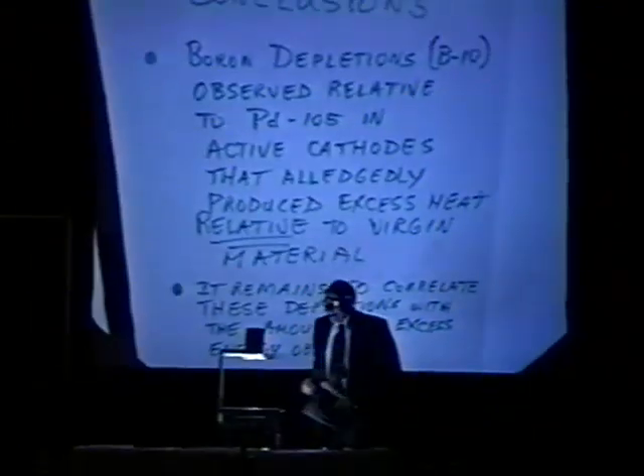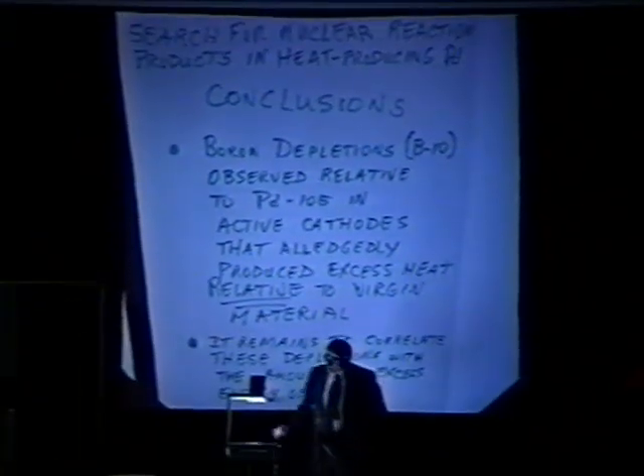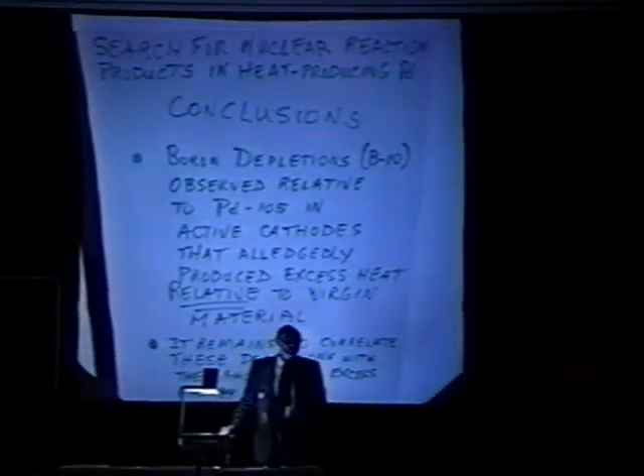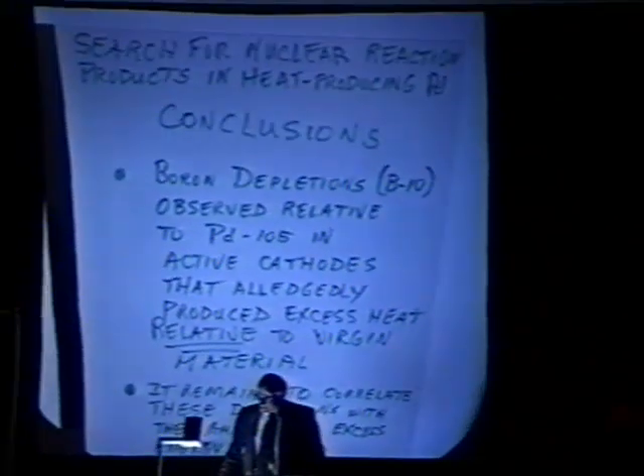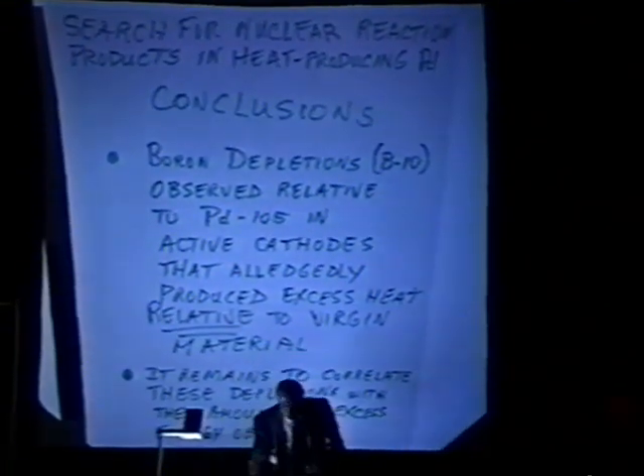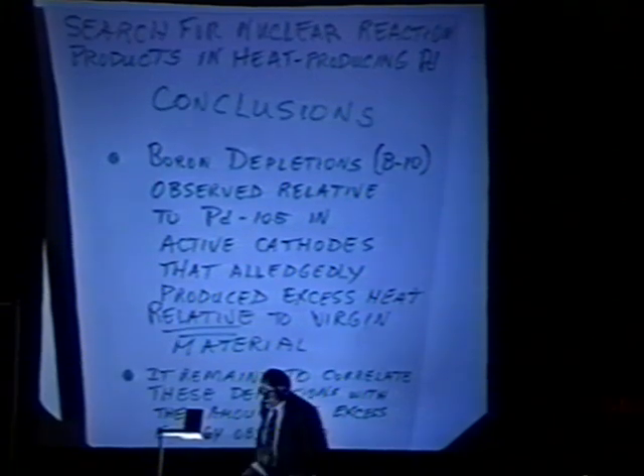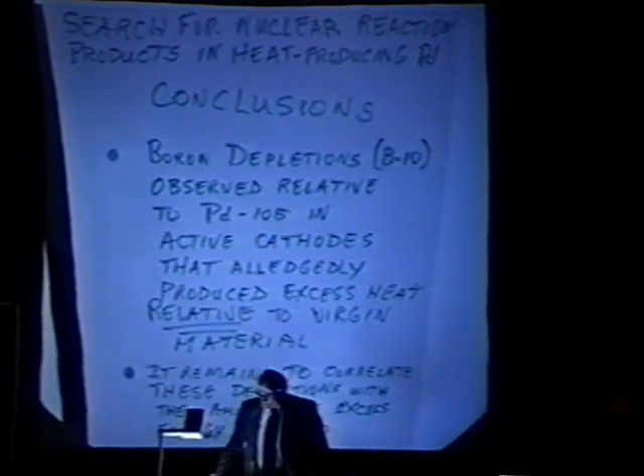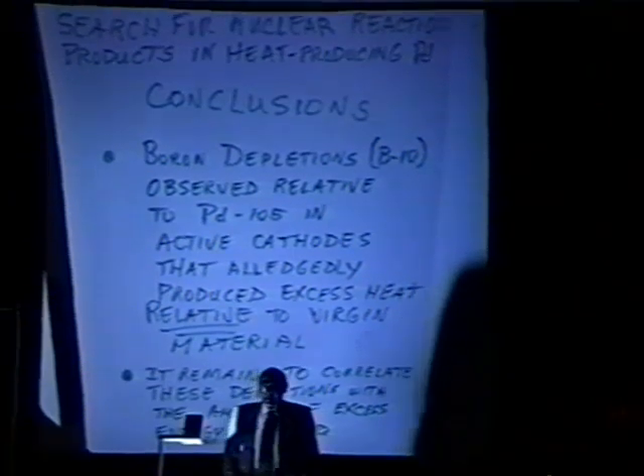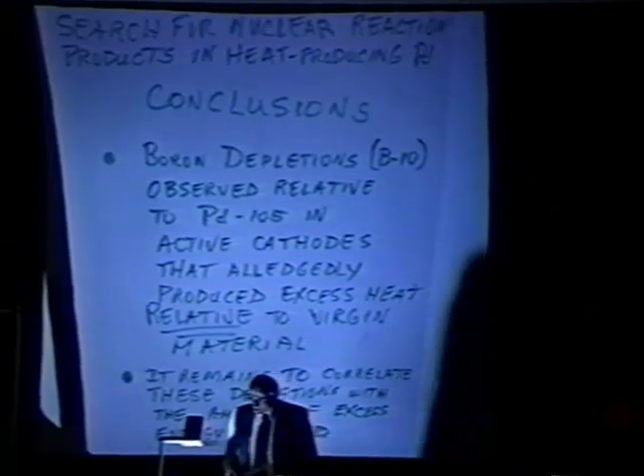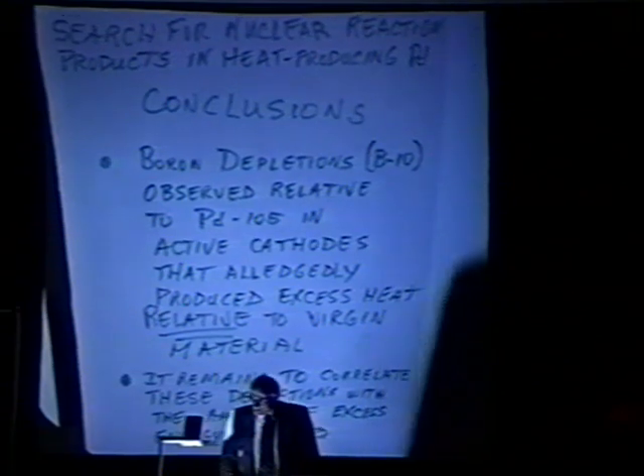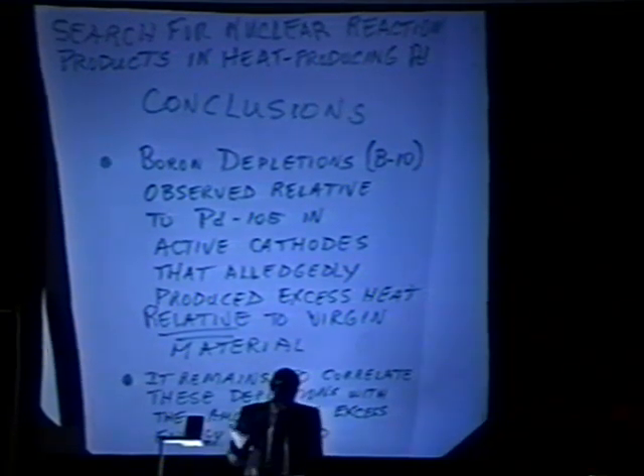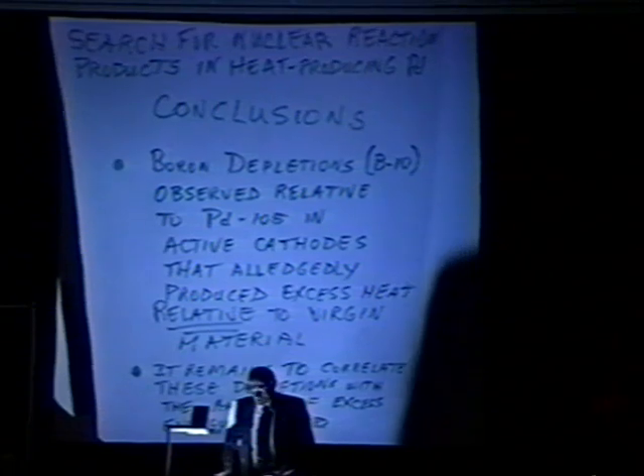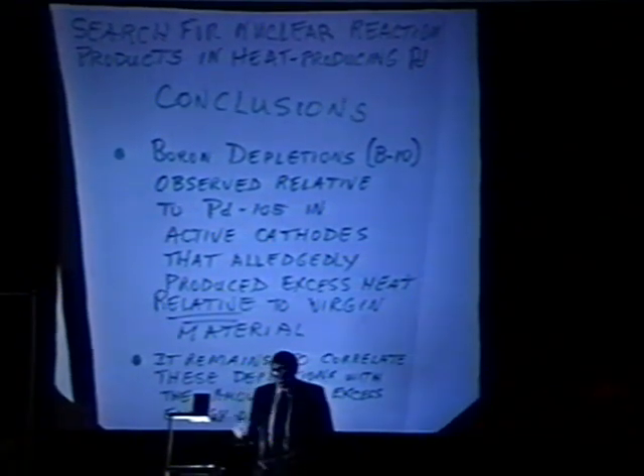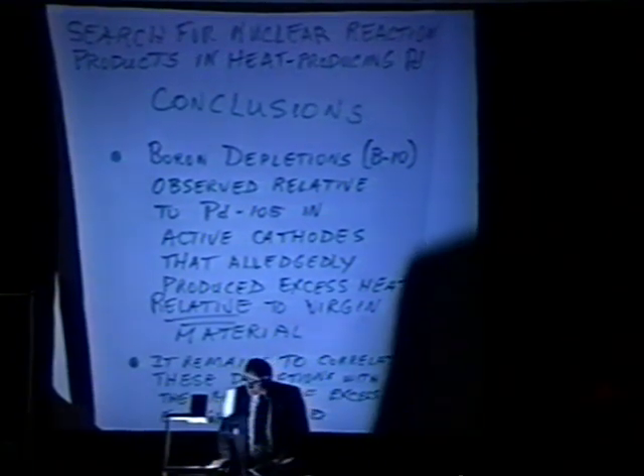Thank you, Mr. Chairman. I'll start with the conclusions of the 5-minute talk. This is a search for nuclear reaction products in old cathodes, doing a little archaeology on cathodes that have been sitting around for several years since they presumably produced, or allegedly produced, excess heat. The conclusions I've drawn from looking at about 30 of them by a special non-destructive method, which I'll show you in a moment, are that we've observed boron-10 depletions. Boron, you know, is a normal impurity in most pure palladium. And I can see boron-10 with this method, but I cannot see boron-11.